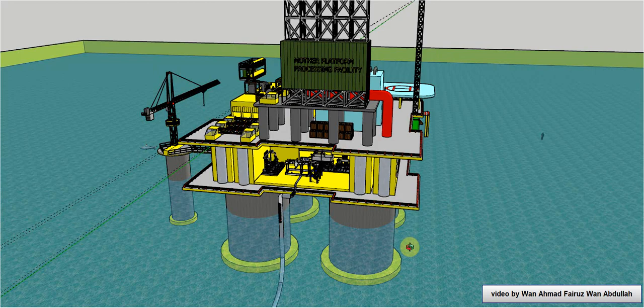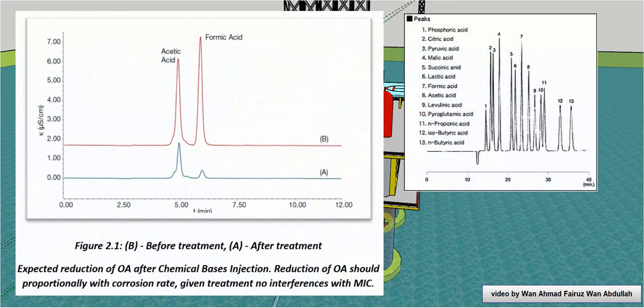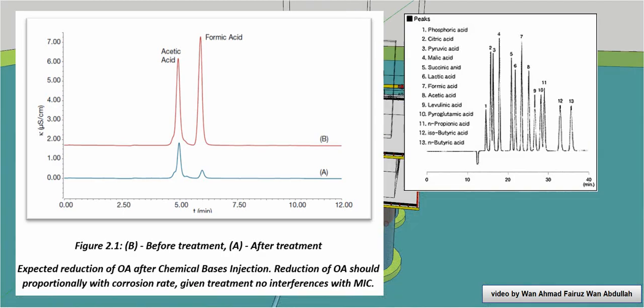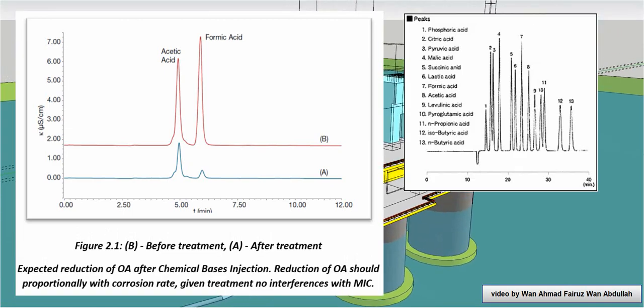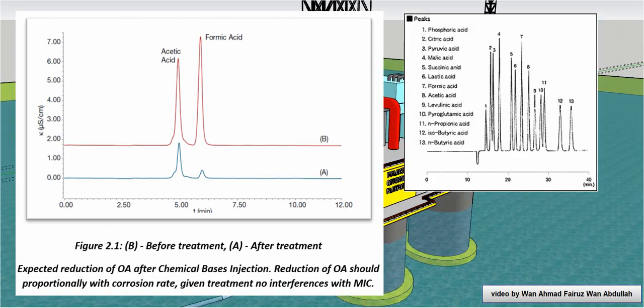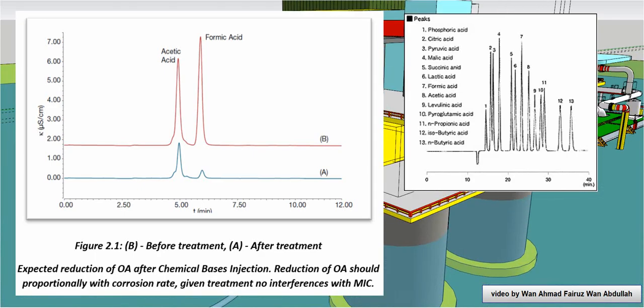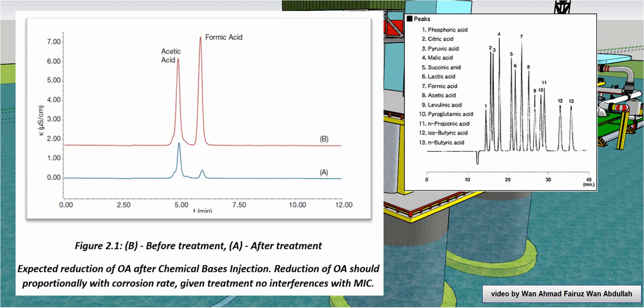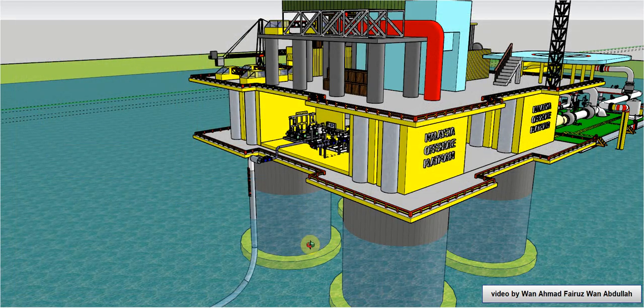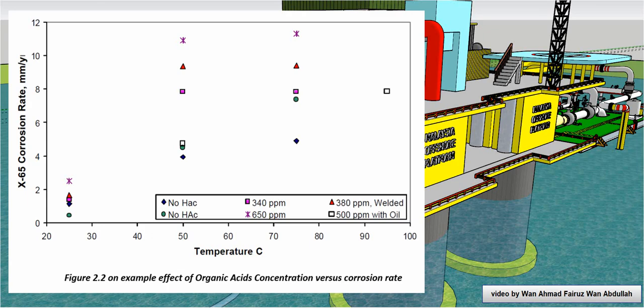To simplify the explanation, let's take the example of this data, which indicates before and after titration with chemical base. From the data, we expect a reduction of organic acid after chemical base injection. The reduction of organic acid should be proportional to the corrosion rate, given treatment with no interference from microbial induced corrosion, SRB. As a function of temperature, the corrosion rate is reduced at lower concentrations of organic acid. This is a very basic figure that we can find in most of the studies.